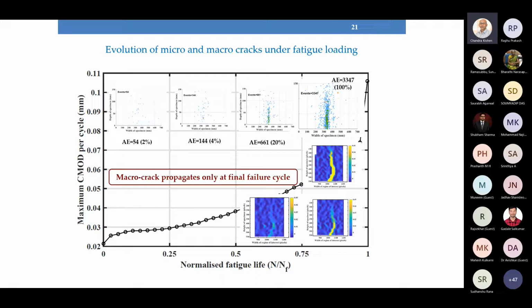So in the case of fatigue, the final failure takes place suddenly. Okay, so the micro cracks which are forming are localized, they are very few in number, but after about 75% of the life, the rate at which the micro cracks form is very large, and they coalesce and form a major crack leading to final failure. So that is a difference. Whereas in the case of monotonic static loading, we see that high energy events are formed right at the beginning, which is seen in the next slide.